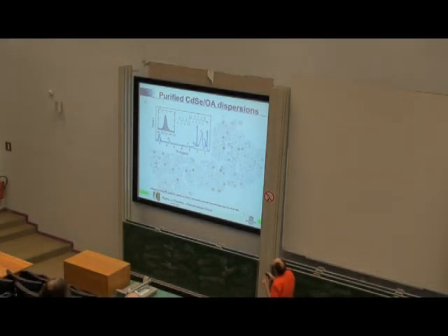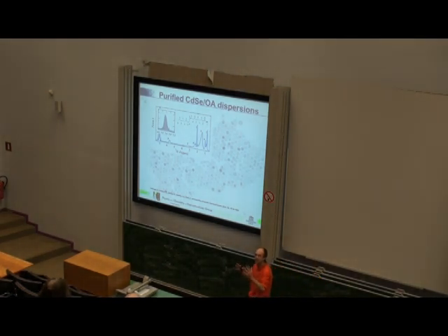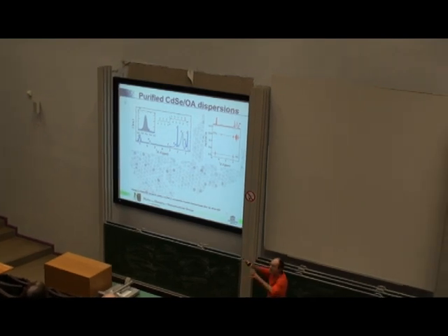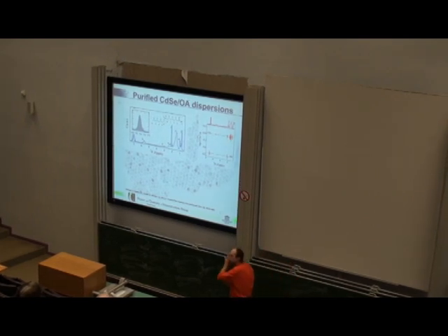Before we dig into that ratio, let's first take a look at this NMR spectrum. You have a frequency axis. The importance of the frequency axis is that you can separate different protons by their resonance frequency, but I will not go into details about that. The most important thing is that you have two types of resonances here. First, a set of sharp resonances: we have one here, one there, and one there. Next to that, you have a collection of pretty broad resonances. One here, and the second is almost invisible. We already know that these broad resonances are from the bound surfactants. The question is, how can we be sure about that?